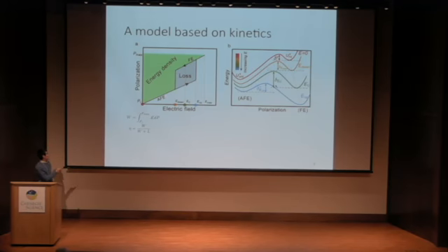The second is we assume the dielectric response of the antiferro and ferro phases are the same and constant. By doing so, we can express this integral as a sum of two terms. The first term is the area of this green parallelogram, which is the polarization of the ferro phase extrapolated to zero field times E down. And the second term is the area of this blue triangle.